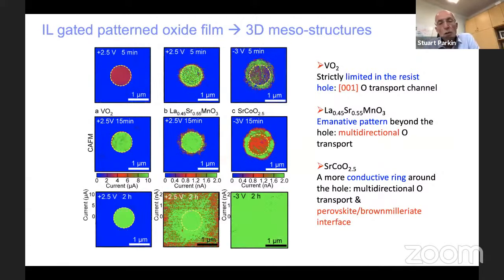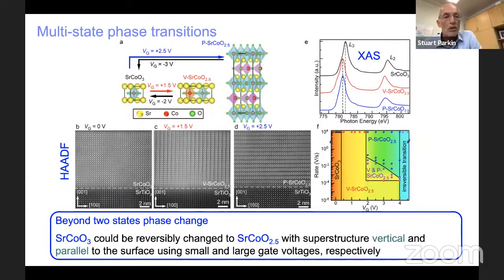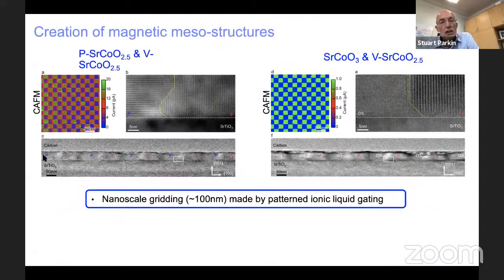So why is it interesting? Well, we can create enormously complex layers, and I just want to give you one example. It turns out we've also demonstrated that, by changing the liquid gating conditions, we can form the brownmillerite with these oxygen vacancy planes either vertical to the substrate or parallel. Each of these are antiferromagnetic but have different structures. And so now we can actually create a patchwork of regions less than 100 nanometers in size. In this case, we've got two distinct brownmillerite antiferromagnetic layers shown here with a boundary between them. It's only 5 nanometers wide.